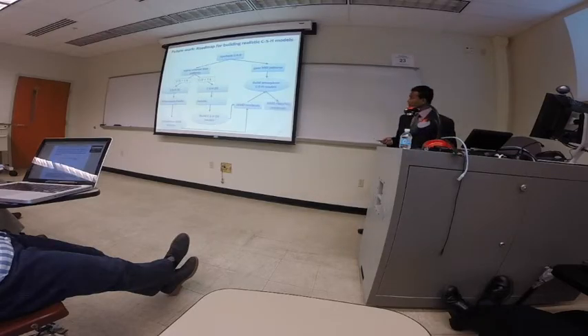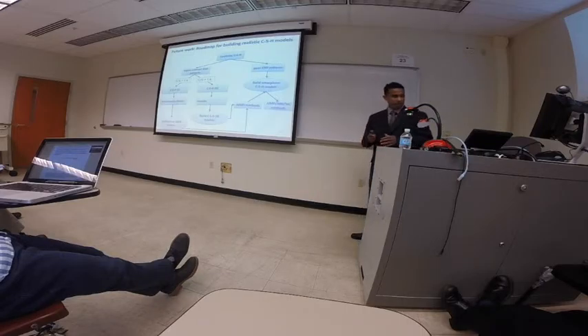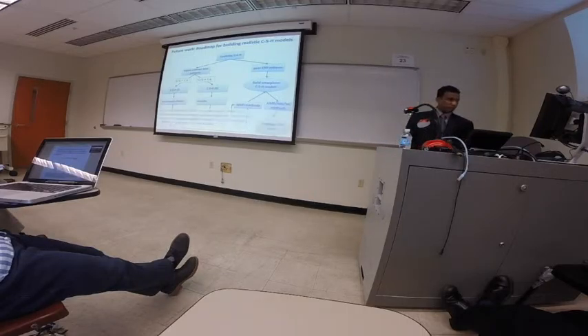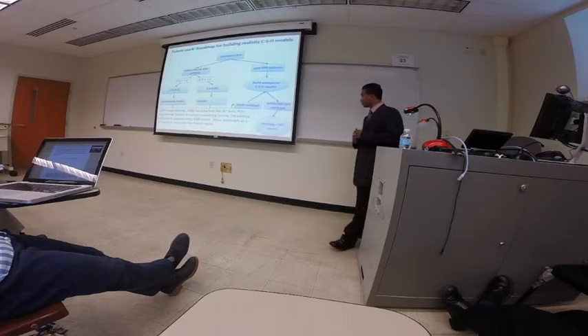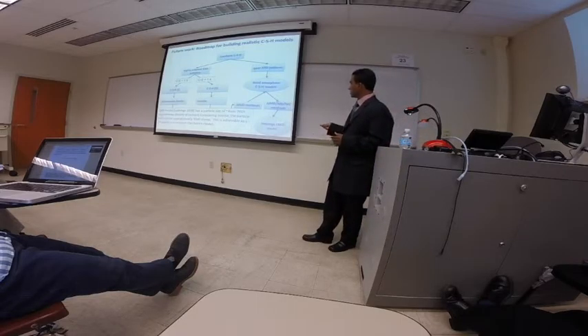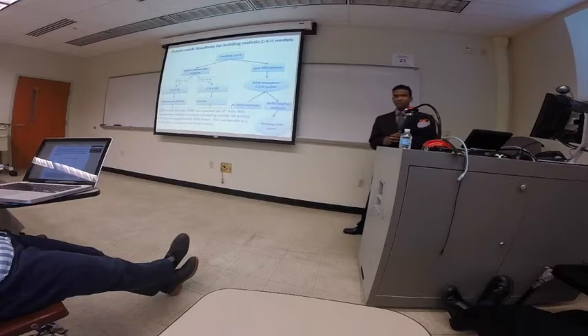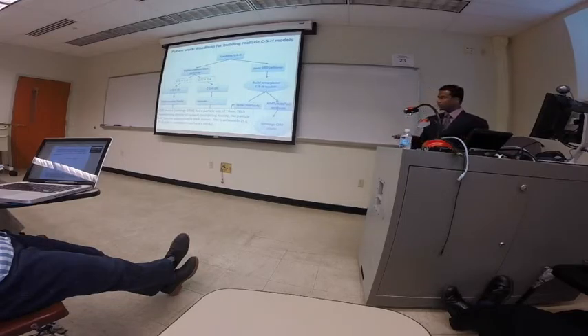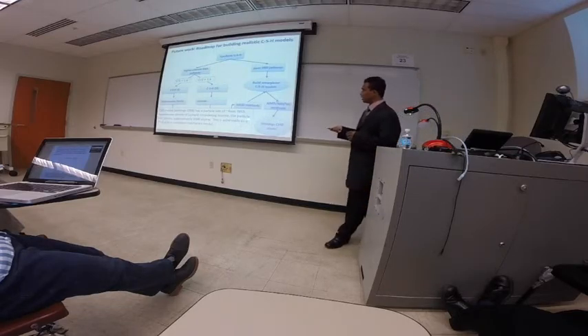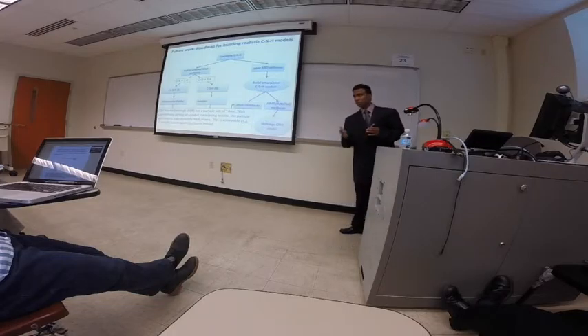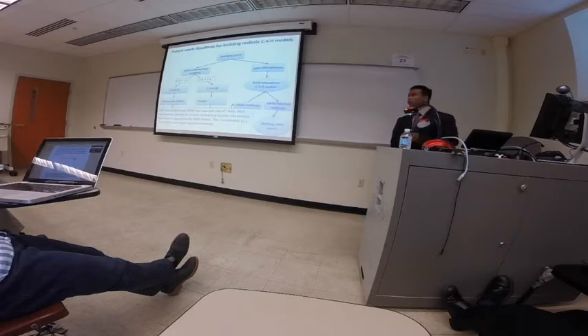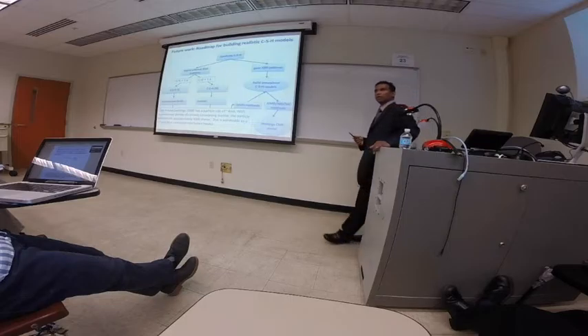And hopefully after that, with further studies using AIMD and MC methods, we might be able to get close to Jennings' CM-II model. Why is this possible? Well, if you do a rough estimation, Jennings' model is on the order of 4 nanometers. Considering the correct density, it will come out to be about 3,000 atoms, which is still doable with molecular dynamics.